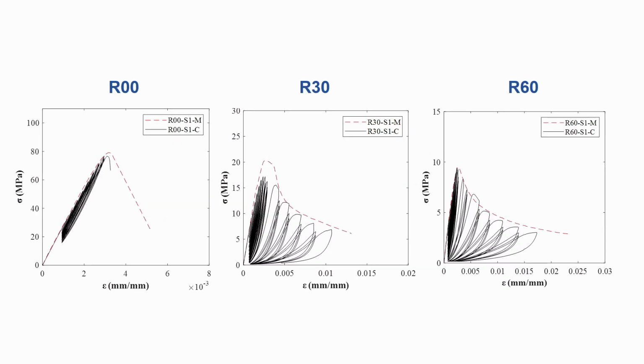Then we went further, we tested those under cyclic compression. So I'm plotting here the stress-strain response for R0, R30, and R60 specimens. And the R0 ones, they kind of failed immediately after reaching the peak compressive strength, whereas the ones with the rubber content, they kind of showed a very nice post-peak cyclic degradation behavior.